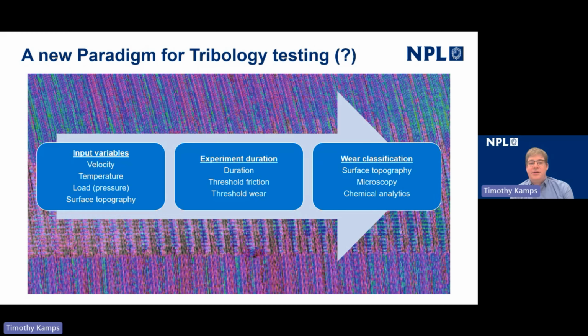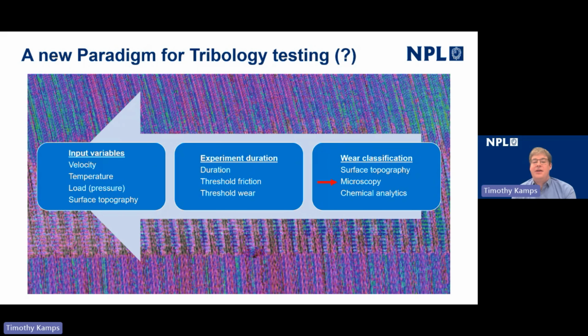But the change in the methodology says, well, actually, if we know which wear mechanism we'd like to reproduce, say a transition from abrasive wear to adhesive wear, we may be able to identify that change by looking at images that have been taken by a microscope. And when we do that, essentially we can start at the other end and we can say to our tribometer, instead of running for a fixed duration or until a fixed friction threshold, run until you see evidence of adhesive wear occurring on the surface of the contact, and then stop the experiment.